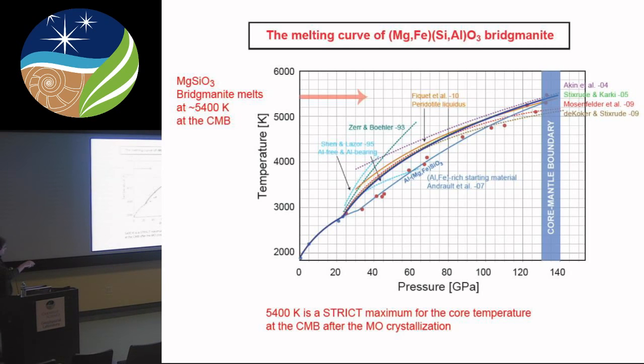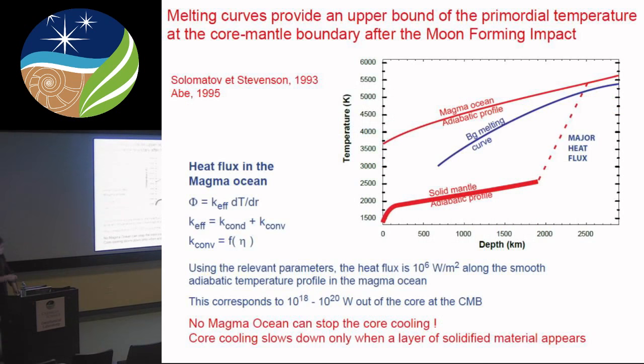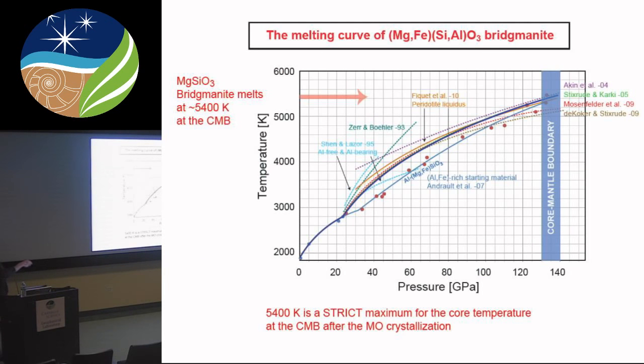And so the experimental work is not that important. It's controversial here. But the models are very good. There are different types of ab initio calculations and also some shock experiments followed by some thermodynamical modeling. And this is basically what we should obtain for what is proposed for the Bridgmanite melting curve. And I argue, based on the previous diagram, that this is the maximum temperature you can get when the Earth starts to solidify. So this temperature here is a maximum temperature for the core after the moon-forming impact.